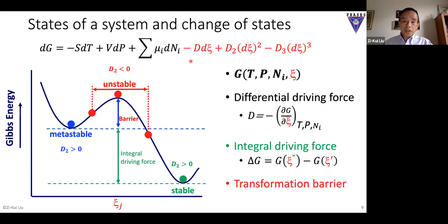So you see, the energy itself actually covers the metastable, stable, unstable, and the barrier. What is barrier? Barrier is kinetics, right? We think the barrier is kinetics. So transformation barrier actually is free energy. So it's between this maximum point and the local minimum point. That gives you the barrier. So think about this one. If we calculate the Gibbs energy, if we get this function, we can calculate the barrier directly. Then we can talk about how this state vibrates, how it jumps. Then we call it the kinetic coefficient. So we get all the kinetics from this free energy. That's what we're going to mention today too, how that works.